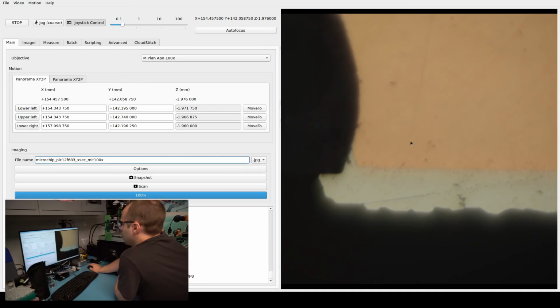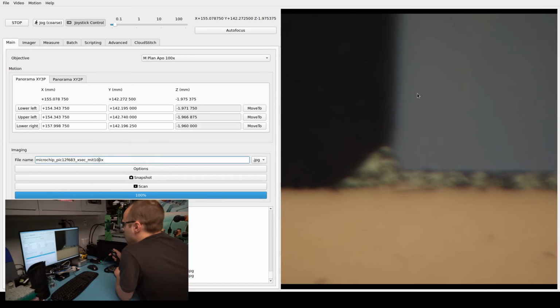We can see that the copper paddle has a tin plating on the bottom to aid in soldering. Then going up to the bottom left corner of the die, looking at the silver epoxy that is holding the die to the paddle and providing both a thermal and electrical connection.